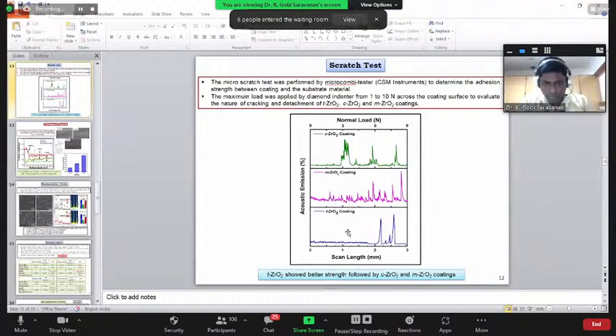For example, this is the tetragonal, this is the monoclinic, this is the cubic. So this is the monoclinic window. Now if you scratch the monoclinic at 0.5 mm itself, some coating is peeled off. For this cubic, it started at 1 mm itself, the coating has peeled off. But the tetragonal zirconia shows nearly 2 mm. It can withstand till 2 mm, and then after that peeling off will be there.